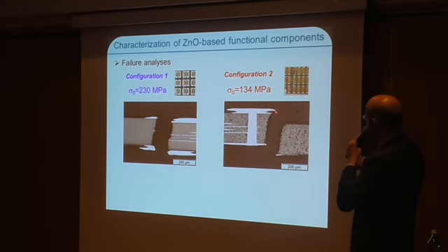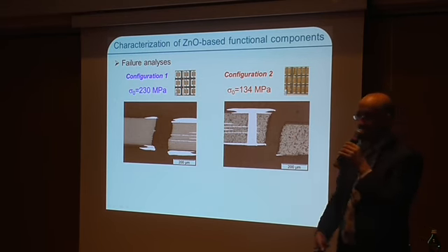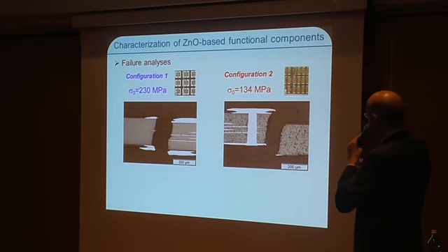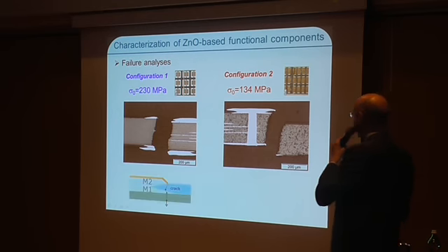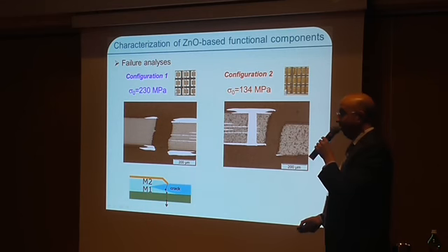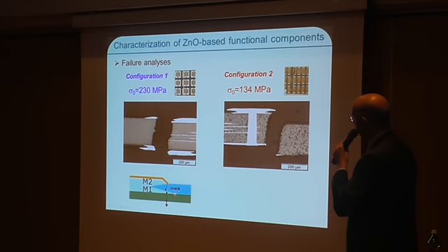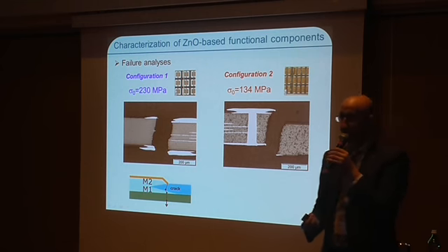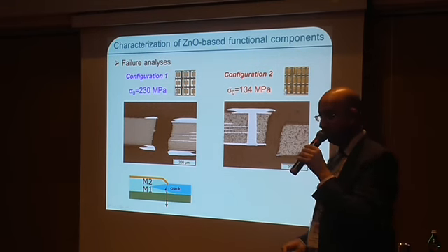Whereas in this configuration, the crack was starting there and just going through the layer. At this particular location, there was no metallization here. So based upon these, we were thinking that maybe that was this metallization. First of all, we identified a critical location where the highest stress concentrations could be.